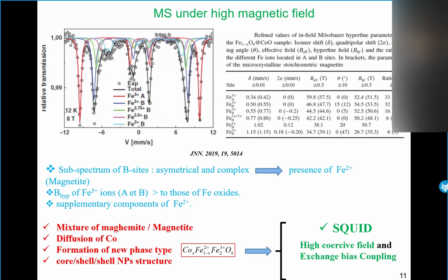If we look at the hyperfine parameters of sites A and B, we observe that the hyperfine fields are bigger than those of iron oxides. That means we have a mixture of maghemite and magnetite, but we also observe a diffusion of cobalt, allowing the formation of a new magnetic phase of cobalt ferrite type with the presence of iron 2+. So we can guess a core shell structure that allows us to understand the high coercive field observed by SQUID.